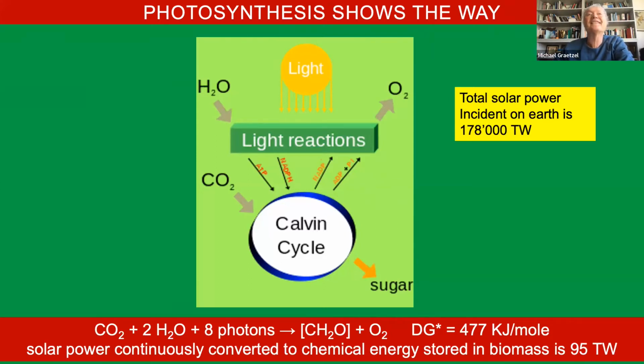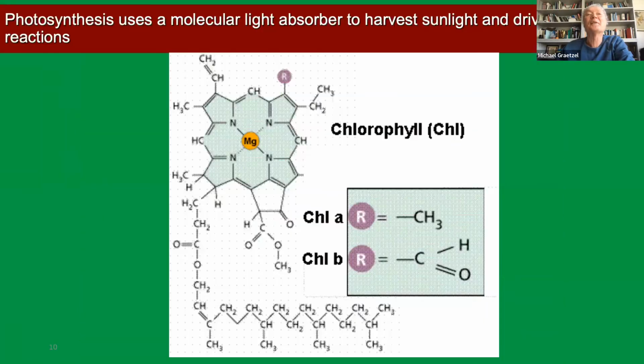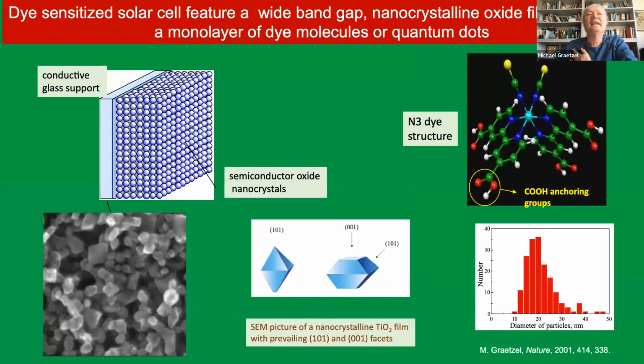Okay, that's a molecular system, where the molecule is the light absorber. And so our approach. I don't want to go too much into the dye-sensitized cells because I have a lot of things to cover today. In a nutshell, our approach was to use these nanocrystal arrays, and these are the electron accepting contact for the absorber. The absorber is a molecular absorber, and it has an anchoring group which binds it to the surface of the oxide TiO2. That's by molecular self-assembly. So it's a self-limiting process. Once you have made a monolayer, it will stop.